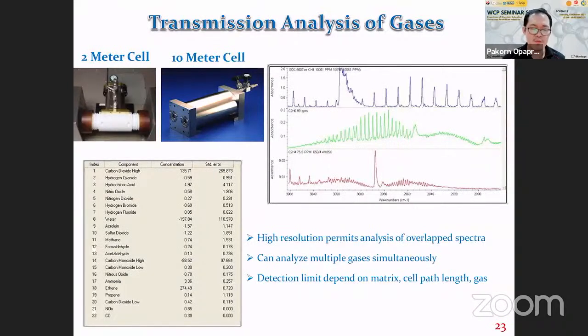So these are examples. If you want to measure a sample in gas form, you need to use a gas cell. Because gas has very low concentration, you need to increase the path length in order to increase the intensity. Path length means the light has to go through your sample, so your sample should be very thick. Therefore, in this gas cell, there are mirrors so that light can go back and forth many times to increase the path length. For example, even though this cell is only centimeters long, the whole path length can go to 2 meters, or 10 meters for this cell. And these are examples of spectra that we get from a gas sample.